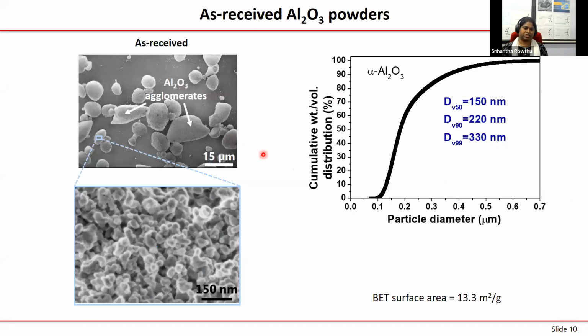So yes, the first thing is that we have to prepare these materials. We have purchased aluminum oxide nanopowders, but because of the very high surface energy they have, they end up being agglomerated. This is an SEM picture of the as-received material, and if you zoom into one of the agglomerates, you are able to see nanograins. If you quantify that, the grain sizes are in the range of 150 nanometers or so.